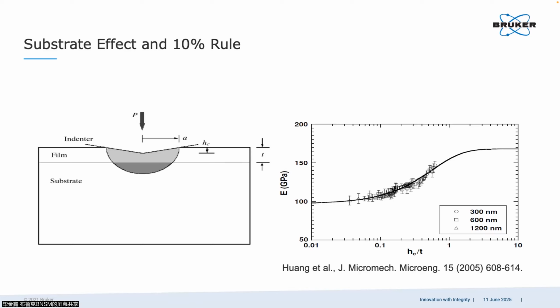For example, if your top layer has a thickness of 1.2 microns, that means if you can make an indentation with depth smaller than 120 nanometers, then you will go into this stable region. So you are able to get the intrinsic mechanical properties. On the other hand, if you go very, very deep and your deformation volume is so big that the deformation is almost 100% coming from the sublayer or the substrate, you will have another stable region, which gives the intrinsic property of your sublayer or your substrate.